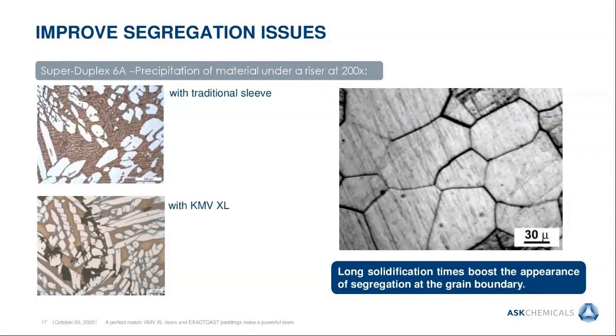Also linked to this idea of reducing the necks, not only will the solidification time be less when using KMV XL risers, but also the possibility of segregations and precipitations of other materials in the neck area. Here we have an example of a super duplex 6A alloy in which a trial was done with two similar feeders. One was made with a traditional sleeve and another one with a KMV XL riser to compare this effect. We can see in the micrography how the segregation and the precipitation is much greater when having these big neck areas. So in the end, it's not only a matter of reducing the solidification times, but also the probability of further defects that may appear with these precipitations.